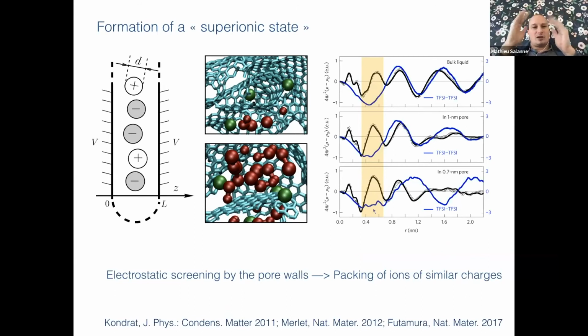Due to the screening, their Coulombic interaction is reduced, and so they are allowed to pack like this and to be in contact. Our simulations came one year after, and we confirmed this by molecular simulations, because we saw the picture that you have here in the middle of ions that are packed together, either anions or cations. And it's only 5 years later that we could do some X-ray diffraction experiments.